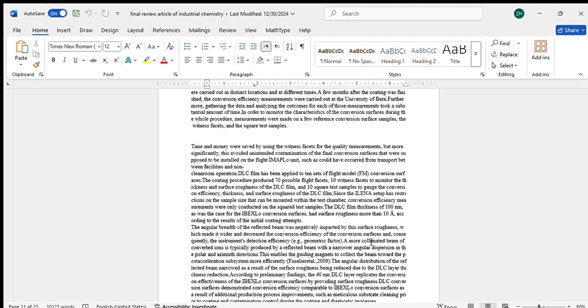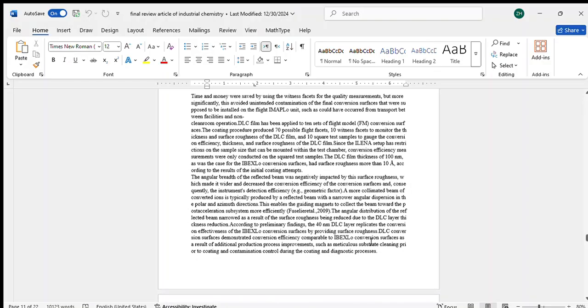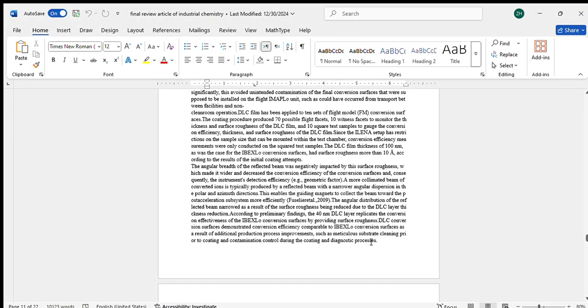IBEX-Lo conversion surfaces had surface roughness of more than 10 angstrom according to the results of the initial coating attempts. The angular breadth of the reflected beam was negatively impacted by the surface roughness, which made it wider and decreased the conversion efficiency of the conversion surfaces and consequently the instrument detection efficiency, for example the geometry factor. A more collimated beam of the converted ions is typically produced by a reflected beam with a narrow angular dispersion in the polar and azimuthal directions.